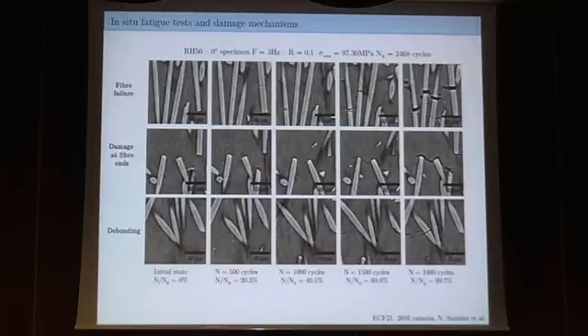You already have fatigue of the fibers. And you can see here that as a function of time, you are developing more damage, but I will come back on that after. So fiber failure, you could also count these failures. You have damage at fiber ends.